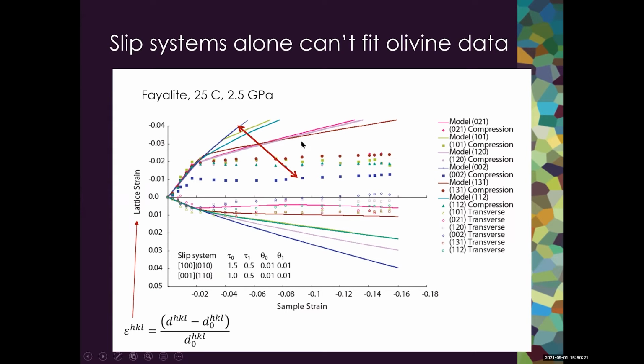And so if we use the slip systems only for olivine in the EPSC model, we can see that the model does not match very well. The EPSC model is work hardening while the diffraction data is not. And we can also see that the peaks are not in the same order for the model and the diffraction data. We have our 021 peak at the top and our 002 reflection lower in the order.